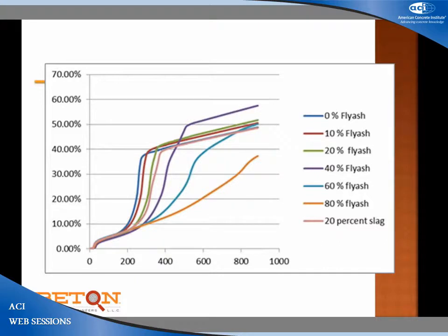But when it goes into diffusion control, you'll notice the higher your pozzolanic content, the longer it takes to go to diffusion control. That's the dilution effect that Ramachandran was talking about. And we have a sweet spot at 40%. At 40%, we got enough in there. As we get higher, you'll notice the shape of the line starts to change. Now we're mostly fly ash.